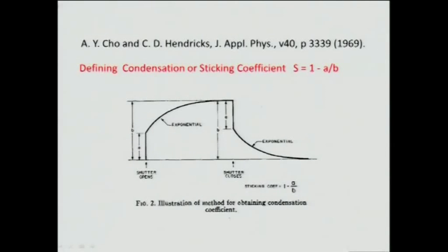What I define is that the sticking coefficient equals 1 - A/B. Let's look at the extreme case. If we open the shutter and A equals B, that means the sticking coefficient equals 1 - 1 = 0. There is no condensation, 0 equals 0. But at the other extreme, if we open the shutter and the exponential curve starts immediately, A equals 0, then that means the sticking coefficient equals unity.